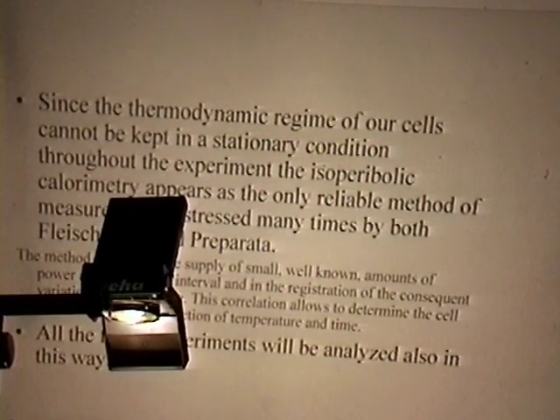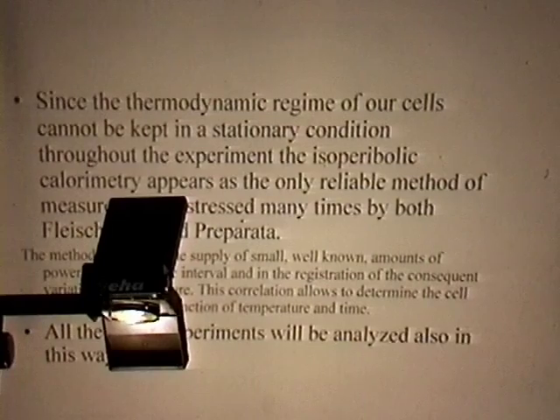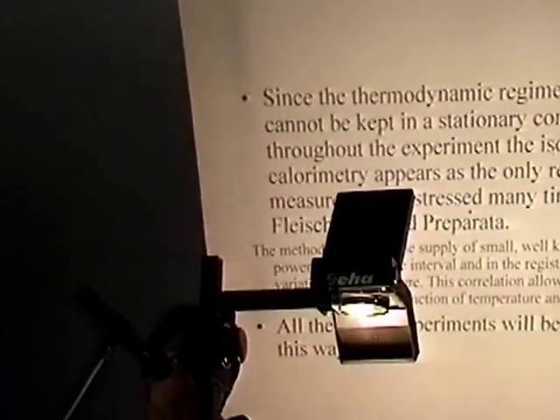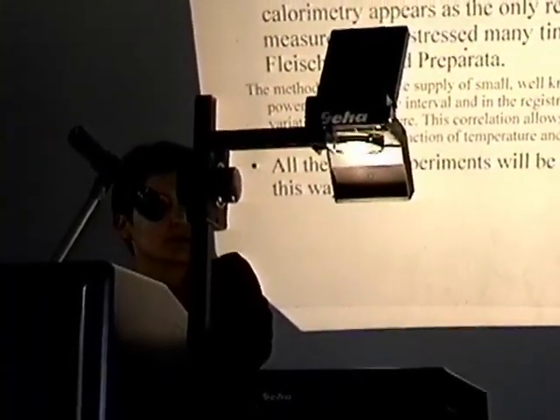So, we discovered at the end that isoperibolic calorimetry is the only reliable method to measure heat excess in this kind of cell. Isoperibolic calorimetry consists in supplying small amounts of power at definite time intervals and measuring the consequent variation of temperature. This allows you to follow eventual changes in the thermodynamic regime of your cell. So we decided to add this kind of analysis to our cells in the future.